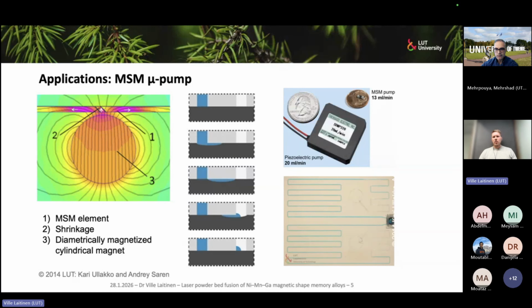So one of the best applications we have developed so far is the magnetic shape memory micropump. How this works is that we have a nickel manganese gallium single crystal, under which we bring a diametrically magnetized cylindrical magnet. And by rotation of this magnet, we generate on this single crystal a tiny undulation. And by rotating the magnet, we can move that undulation across the single crystal surface. And in effect, we can use it to carry liquid. So it works in a very similar way to how human swallowing works in the throat.